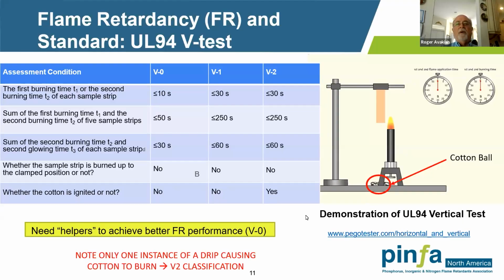So this, I think many people are familiar with, is the so-called standard UL 94 V test. You can see that you've got a Bunsen burner here with a given amount of heat output and a certain height of the flame. And you can see that you've got this bar in the schematic here in a vertical orientation. You obviously bring the burner over to it, hold it there for 10 seconds, then pull it away, and then take it back again. What you're looking at is, how long does it take for the combustion to extinguish? How long is the flame burning? Then you add up those number of seconds.